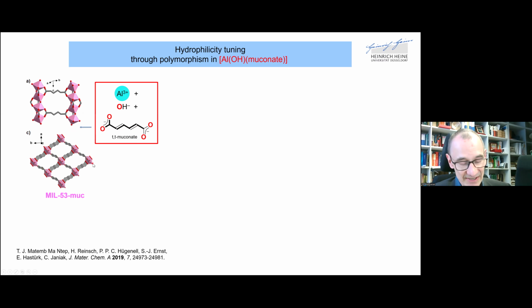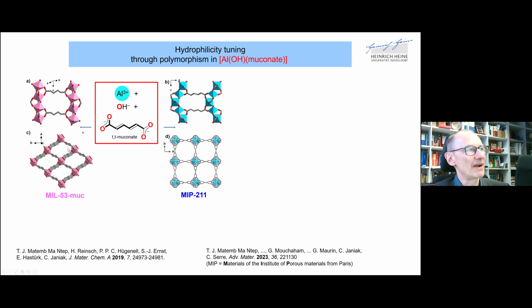Depending on the synthesis condition, we actually came across a second polymorph. One had a more rhombohedral channel arrangement, and the other a square channel arrangement. Otherwise, the building blocks were exactly the same: one aluminum, one hydroxyl group, and one muconate linker. So the formula did not change. So we have two polymorphs here.